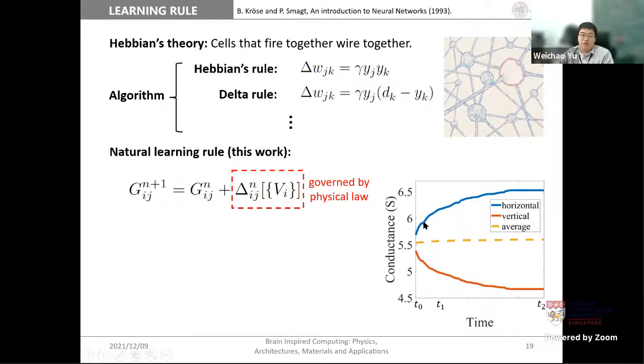First of all, the conductance of this texture, let's say the horizontal conductance, will increase for a given voltage. This corresponds to the positive feedback process according to Hebb's theory. However, such a positive feedback process is not sufficient. Otherwise, the conductance will increase and finally explode, which will never converge. So there's another feature embedded in this system, which is the competition between synapses. When one synapse is strengthened, the other synapses, let's say the vertical synapse, will be weakened. For the simplest square film case, the increase of the horizontal conductance leads to the decrease of the vertical conductance.